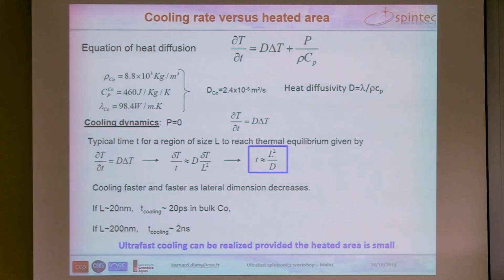So if you are interested in the cooling dynamics, when the media is moving underneath the plasmonic antenna, the media is heating up when it passes just below the plasmonic antenna, and as soon as it moves away from the plasmonic antenna, it starts cooling down. So once it has passed on the other side of the plasmonic antenna, the source term here is equal to 0. So we have the time variation of the temperature, which is given basically by diffusivity times the Laplacian of the temperature field. So this can be approximated this way.